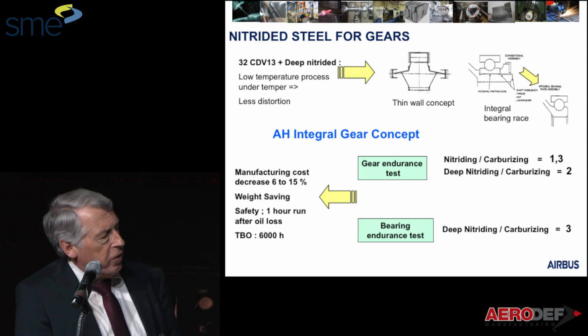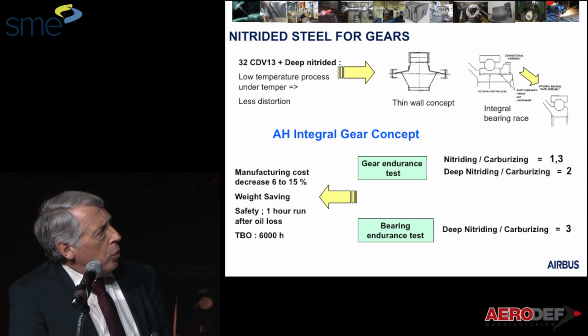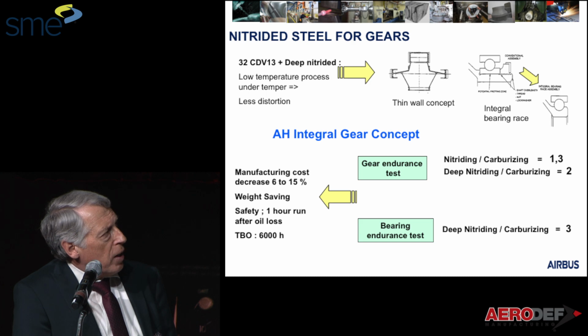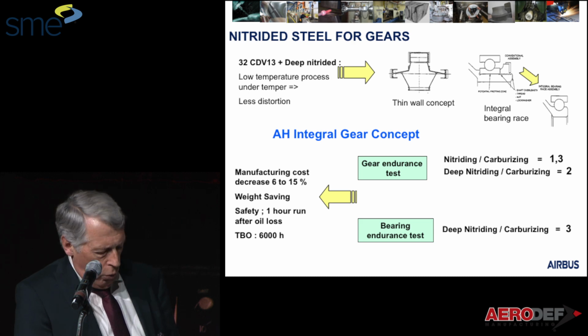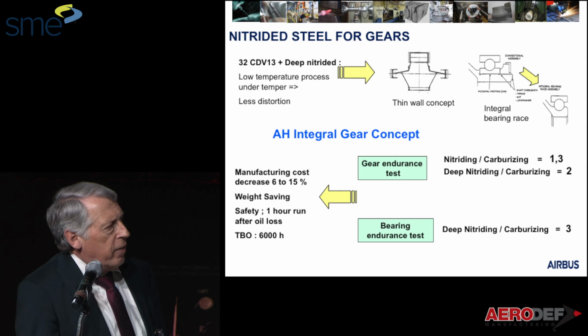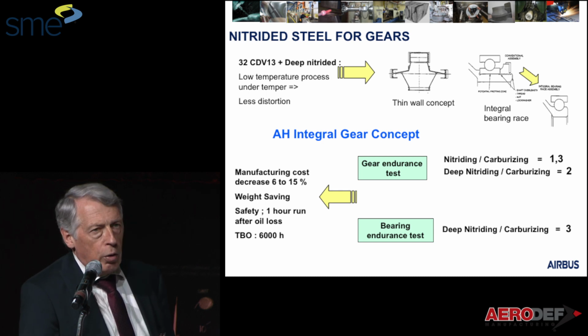But thanks to this technology, we are able, with this material, with a low temperature process, lower than the tempering temperature, to design very thin parts without very high distortion, and to integrate the bearing track into the material due to the fact that we have a good hardness of the material on the layer. By the way, as a reference to carburizing, it was possible to multiply by 3 the endurance on the bearing, and to multiply by 2 for the gear.